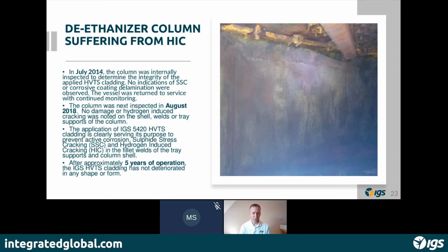And what they found was that there was no breakdown of the thermal spray system, as we would expect. The alloy itself is resistant to the environment, and so long as you have a sufficient application process so that you create an impermeable barrier, that alloy is going to sit on the surface quite happily and stop any further corrosion of the substrate. So after 5 years, we didn't need to do any repairs. The client put the column back into service.